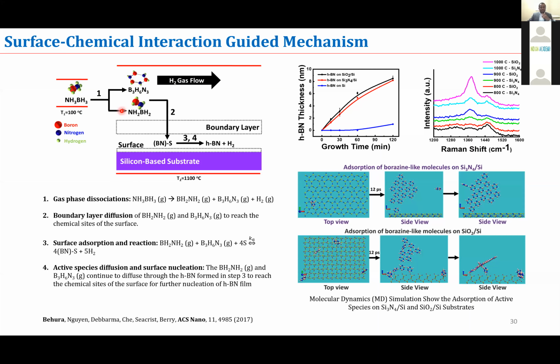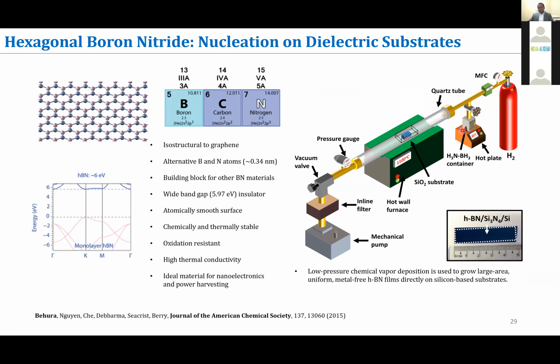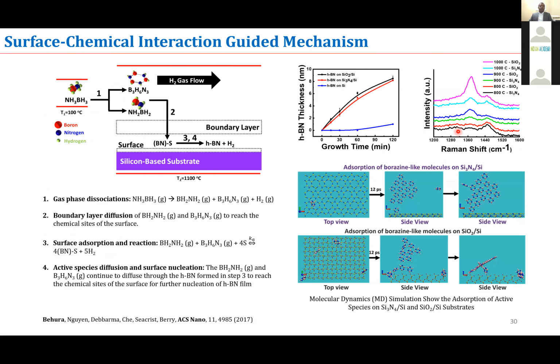So these are the constituents that this ammonia borane breaks down into at a temperature of about 100 degrees Celsius, in a separate chamber that I can show you here. In this separate chamber I place the precursor and heat it to 80 to 100 degrees Celsius, and then I open this valve, and the gas comes into the main chamber, where we have a silicon oxide substrate sitting in the high temperature furnace, at about 1100 degrees Celsius. This precursor gas comes in, and then boron nitride formation happens directly on silicon-based substrates.